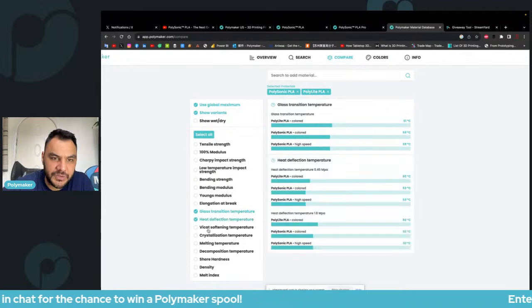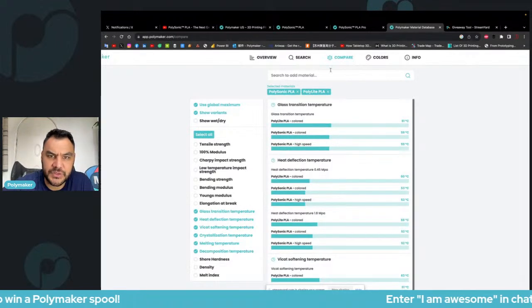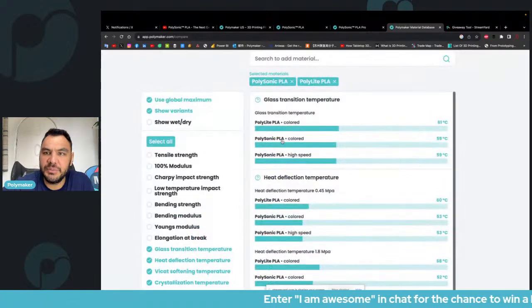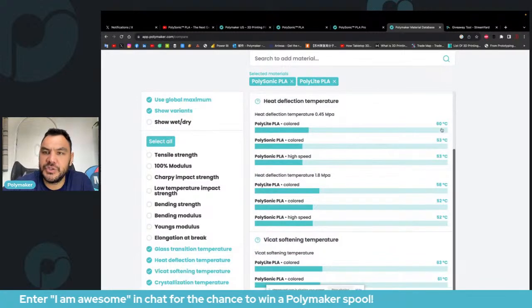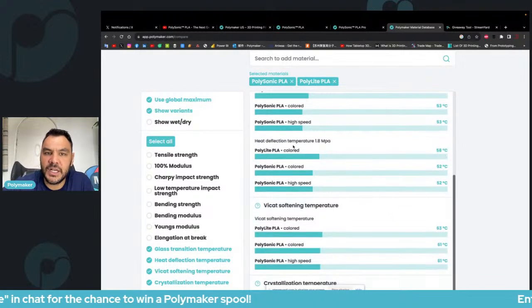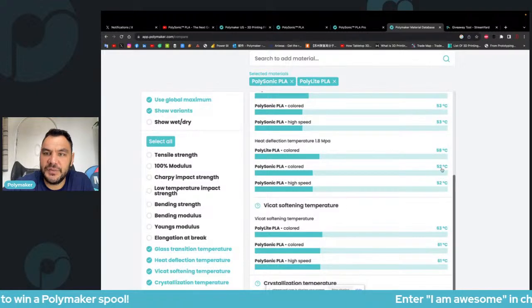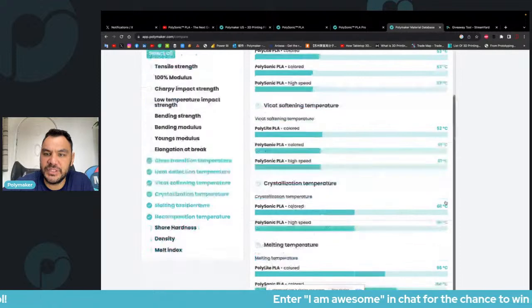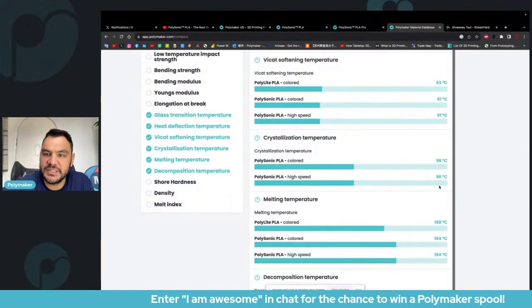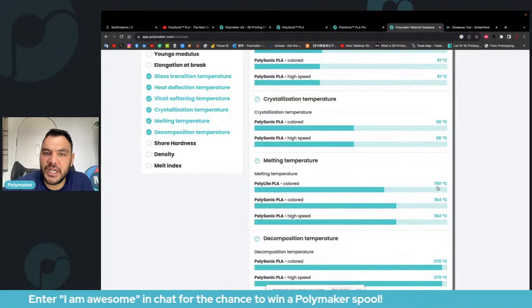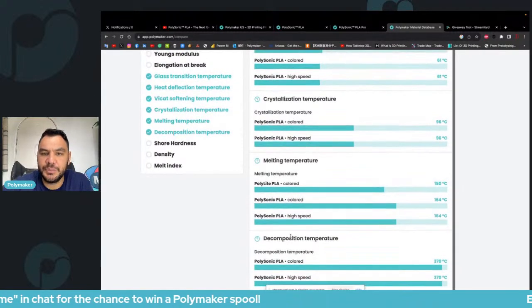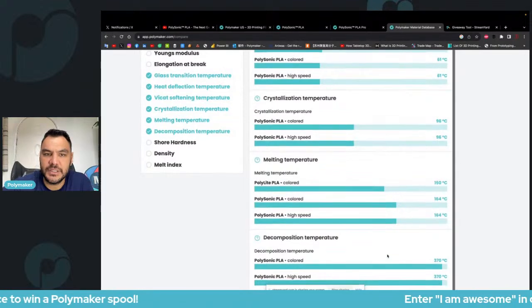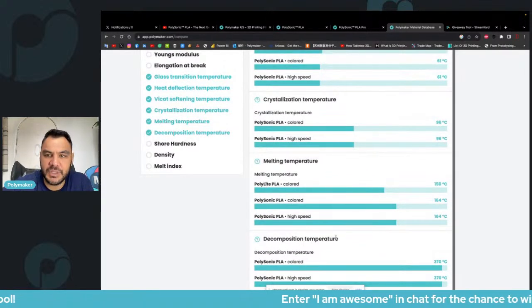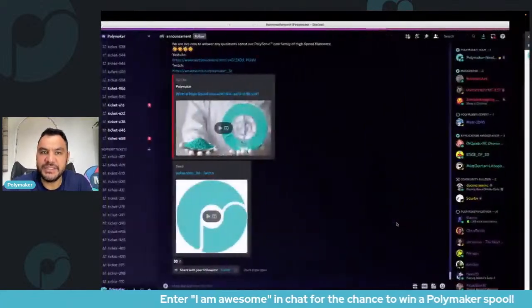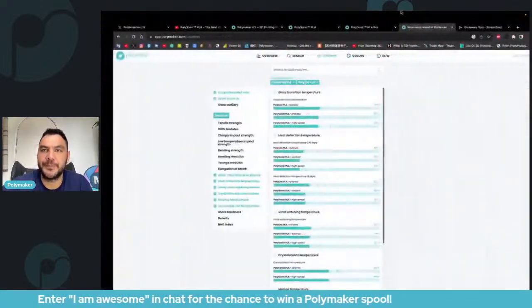Actually, you can go here. Glass transition heat deflection temperature, crystallization, melting temperature, decomposition temperature. So you can see PolyLite PLA and Polysonic PLA are basically the same. Glass transition temperature 61, 59. Heat deflection temperature 60, 53. HDT at 1.8, 58, 52. VICAT softening temperature 63, 61. Crystallization temperature 96, 96. Melting temperature 155, 164. And decomposition temperature 370, 370. Oh, actually, we don't have the one of Polylight. So it's basically the same from that point of view.